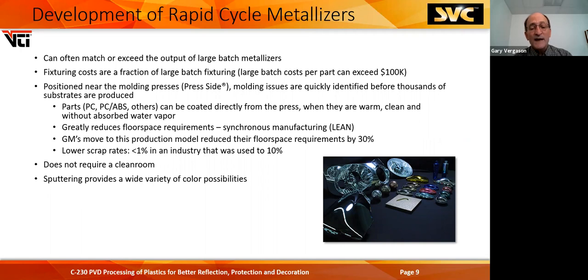In General Motors, actually, when they went to the full rapid cycle setup, they reduced their floor space requirements by 30%, which was huge. Much lower scrap rates. It's below 1% in an industry that was used to 10%. It does not require a clean room, and the sputtering technology provides a very wide variety of color possibilities.